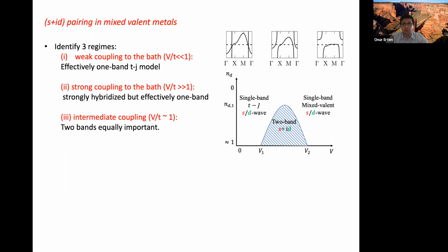But I mean, one of the ways to understand is just fermiology. One can draw the bands where they cross and then draw the gaps. The D wave would have line nodes and the S wave will have nodes like this. And if you have this two band regime, you can show that the S wave pairing is energetically comparable to D wave. Normally the S plus extended S wave is not favorable because its nodes lie on the, no, the extended S wave is like a diamond, yeah. So its nodes lie on the half-filled Fermi surface.